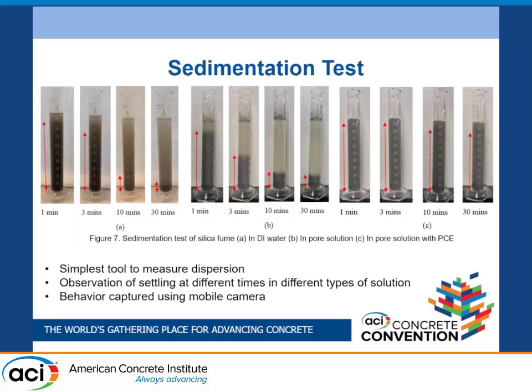The next test we conducted was the sedimentation test. This is a very simple test, yet it's effective. For this test, we take a weighted amount of sample, with a known weight based on the bulk density of the sample, and mix it in about 100 ml of water in a Resodyne mixer.